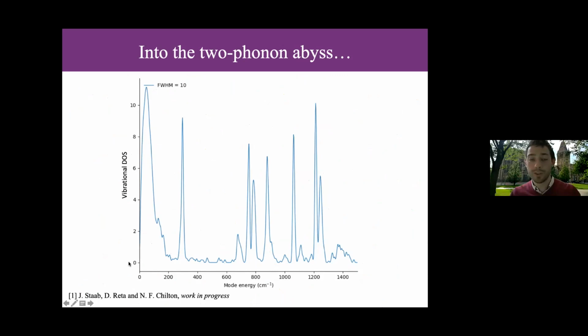and then this big lump at the bottom is all the pseudoacoustic modes of the lattice. That is, little motions of molecules moving between each other, or slight rotations. And of course, these will project, if you do the analysis, onto vibrational modes of solvent and molecule. But in general, these are the very low energy modes that are going to contribute to the Raman regime.